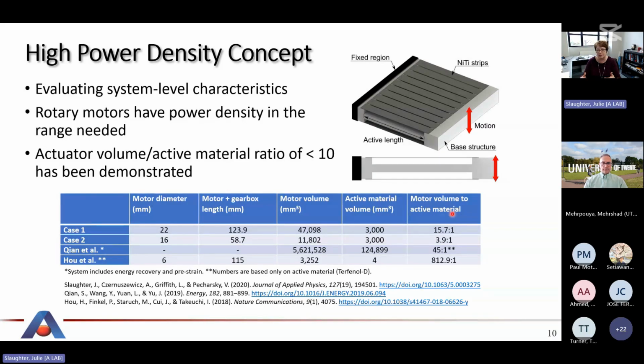And so we want to at least be at that same level for elastocalorics in order to really start to be a commercially viable system. So what we looked at in this double-sided structure is, how much material volume, and we ignored a lot of the structure, but we did say, okay, what is the active material volume to a motor ratio? And we achieved actually a very, very good result of just under 4 to 1.